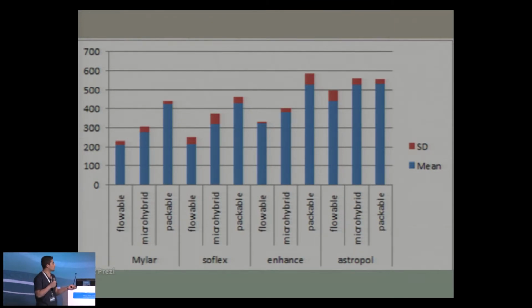This is the control group, the first group with 10 samples, and these are the 3 polishing systems in different groups. The Mylar or control group recorded the lowest value among all groups. But among the polishing systems, Soflex recorded the lowest value after finishing.